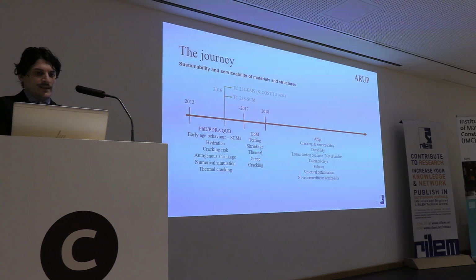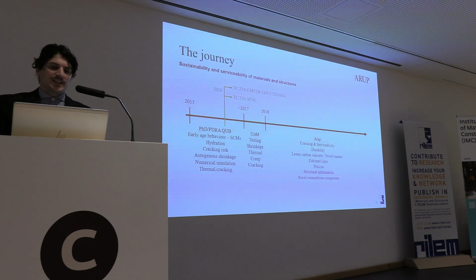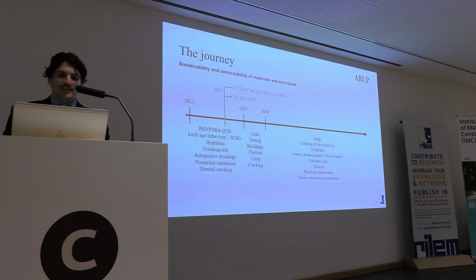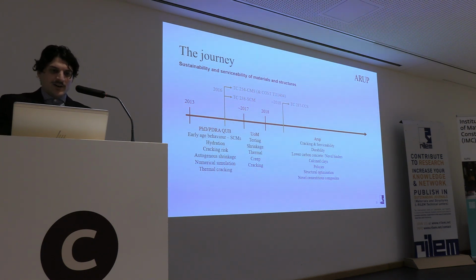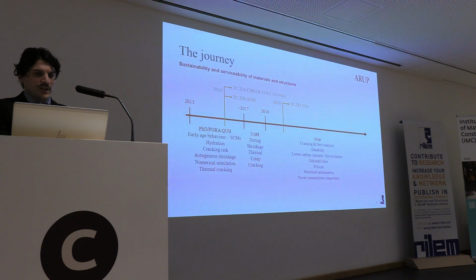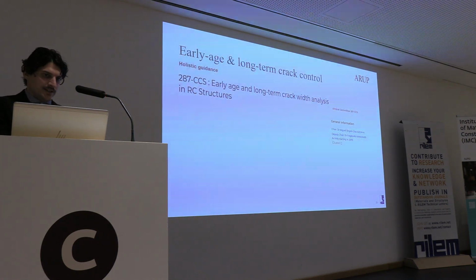But as importantly, I moved into my current role in ARUP, which is quite a big player in cracking, serviceability, durability, very much into lower carbon concrete and novel binders, calcined clays, policies, structural optimization, and other cementitious composites. It was quite important because during that time we initiated the technical committee on early age or long-term cracking, TC287. And okay, previously we were looking into the massive concrete structures as being the main candidates for cracking risk, but then cracking is an everyday problem in concrete across different timescales.